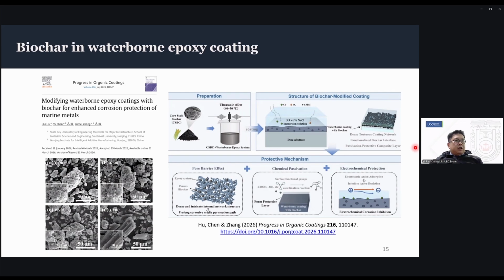In this study, they were playing around with different feedstocks as well. I won't go into the details, but they found that the cornstalk biochar gave them the best results. They argue in this article that this is due to the pore structure, which forms multiple pathways that slow down the penetration of corrosive species from reaching the metal surface.